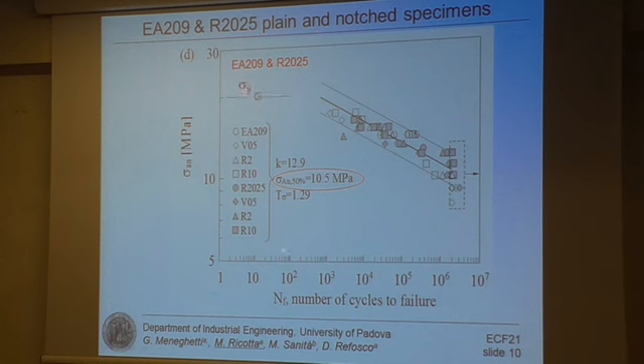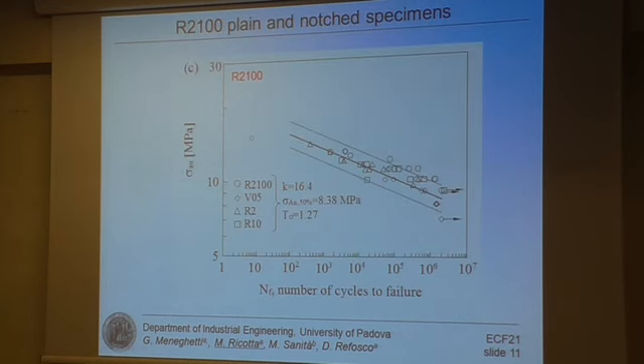We can see here that in the low cycle fatigue zone, the fatigue strength of the material is practically equal to the yield strength of the material. In the case of totally recycled compound, we can see that also in this case we can draw a single scatter band in terms of applied stress amplitude referred to the net section. Therefore, also this compound can be considered as notch insensitive, but with a different and lower fatigue strength, having a 50% survival probability, referred at 2 million cycles, equal to 8.4 megapascal, and a different slope of the fatigue curve.